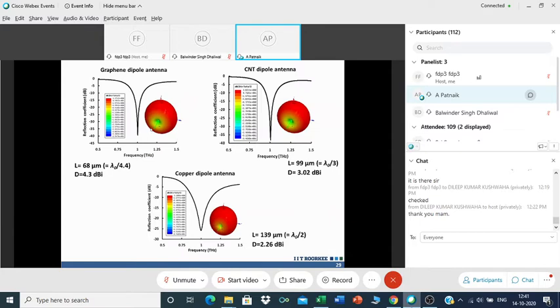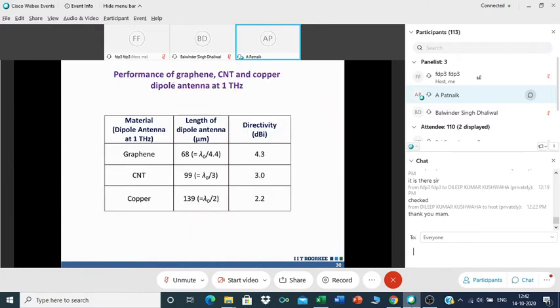So this first one for graphene is 68 micrometer length, this one is 99 micrometer length, and this is the copper one, 139 micrometer length. And directivity wise also, it's giving better performance. So from these two studies, we found that out of all the materials that people are preferring for making terahertz antennas or flexible antennas, graphene gives better performance. Graphene antennas are that's why preferred for making these terahertz antennas.